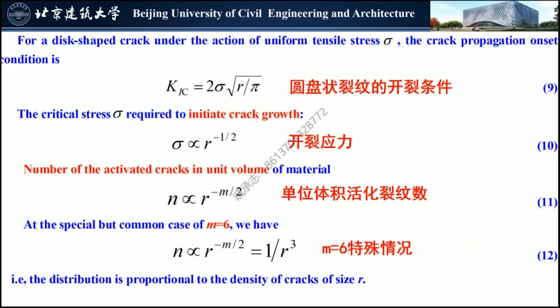For a disk-shaped crack under the action of uniform tensile stress, the crack propagation onset condition is expressed by equation 9. The critical stress sigma required to initiate crack growth is expressed by equation 10. The number of activated cracks in unit volume of material is expressed by equation 11. In the special but common case of m equals 6, we have equation 12, which means that the distribution is proportional to the density of cracks of size r.